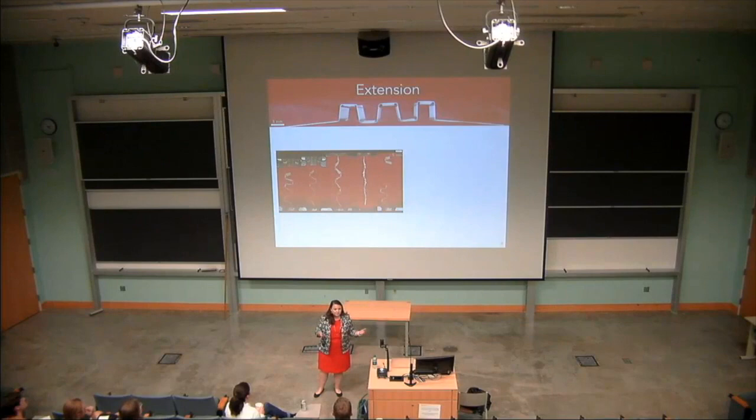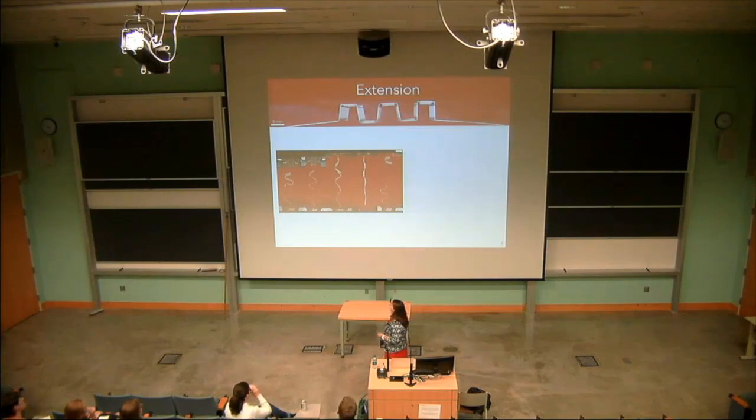So there's two different areas I said I'm going to talk about, one of which is extension. Now, if we're looking at this image, if you can imagine essentially grabbing the two far ends and pulling them outward and extending at a steady strain rate, that's the image you're seeing on the bottom portion of this slide. So as we move this upper grip in an Instron upward at a steady strain rate of 10 millimeters per minute, we can watch the entire thing essentially flatten out until we reach a point of breakage, and that's when the sample just breaks on its own.